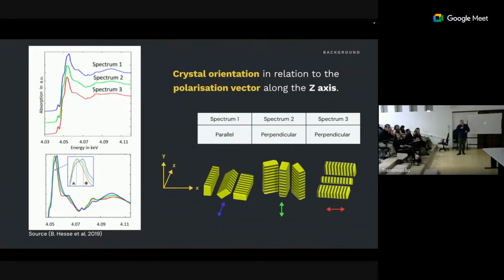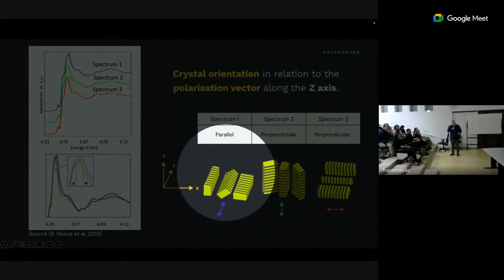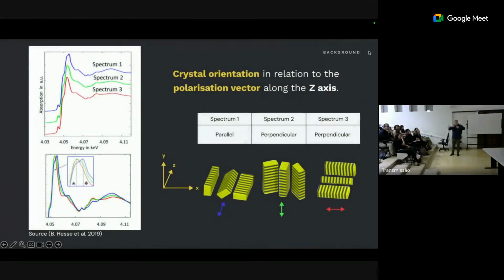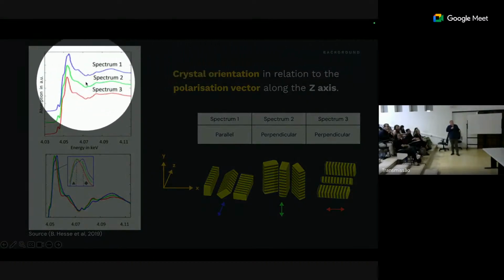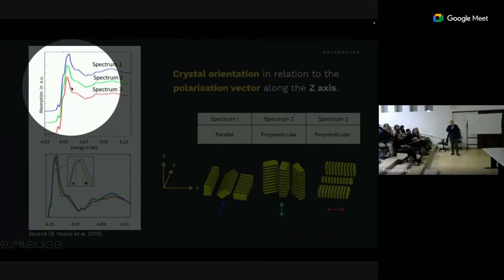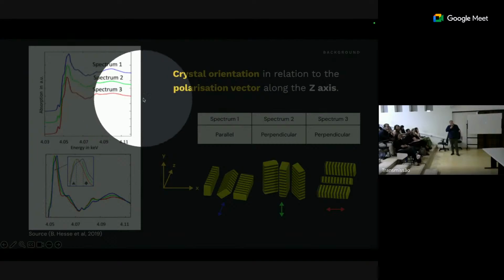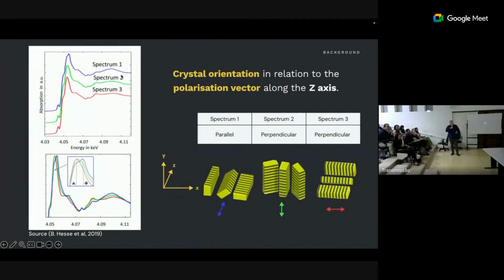So for this technique, we identified that there was an interesting relationship between the direction that we took our polarized light, so either straight to the crystals in that direction, or crystals in that direction, with a very subtle change in the way that the calcium would be projected in this spectroscopy technique. I'm trying to keep it as simple as I can in this one. And so we exploited that by saying, well, if we start to image the tooth surface in different ways, knowing that we're changing our polarization, we can start to say, well, those pixels are orientated this way, these pixels are orientated this way. But we run into a problem.